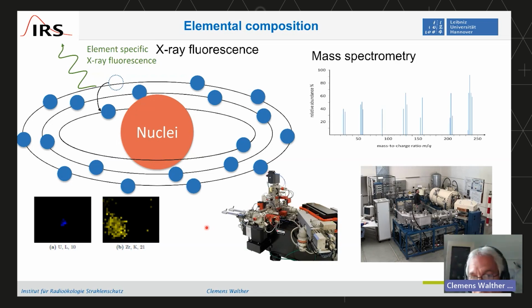Very good. Another option, what is done very frequently, is mass spectrometry. Here you see just a generic mass spectrum, and that mass spectrum can be obtained by different methods. So typically you have low sample volumes and have a very low number of atoms to be detected. Sometimes you even have to suppress against neighboring masses or a high excess of other isotopes. And two out of many methods you could use are the AMS, you see here, or you can use SIMS, secondary ion mass spectrometry, and the secondary ion mass spectrometry, a little different instrument from what you see here, will play a role in the second part of this talk.